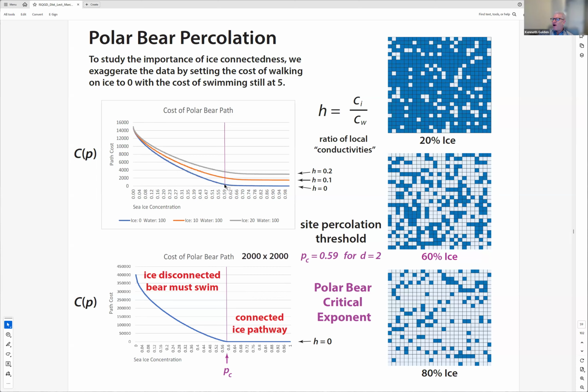That's where it goes to zero. Almost, you can see it exactly here. This is a larger sample than that. And anyway, it's just like percolation theory. So basically, I looked at this and said, oh, I bet there's a critical exponent. So we measured the critical exponent, and the critical exponent that describes the vanishing of the energy cost to a polar bear matches almost exactly the 2D conductivity universal lattice percolation conductivity exponent.